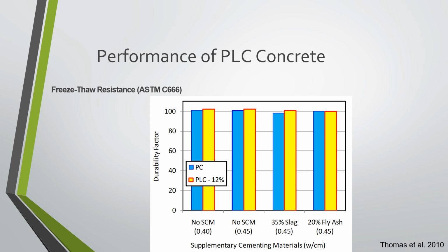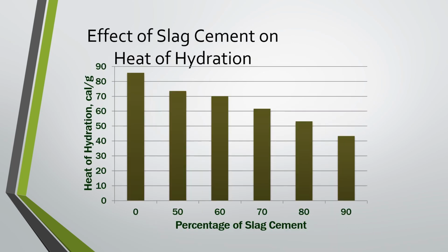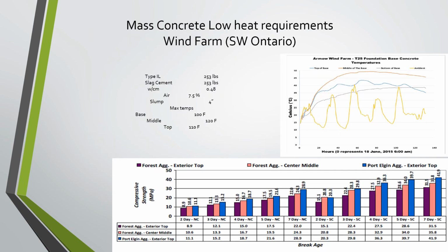When we look at freeze thaw, we're seeing the same thing on here. When we look at heat of hydration, we're seeing the same results. One thing we are seeing with the PLCs is the initial temperature may go up, but the long-term 28 days, 7 days and all that, when we do the isocalorimetries, is actually a little bit lower. So in this case, the PLC and the slag will lower those numbers. But like anything, you want to do the testing and you want to check it.